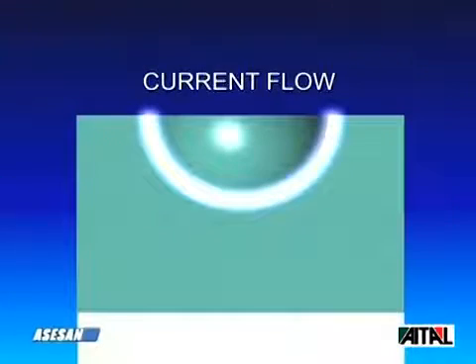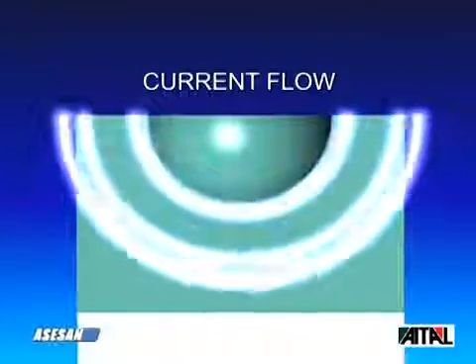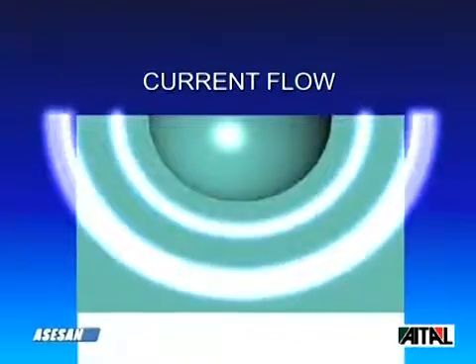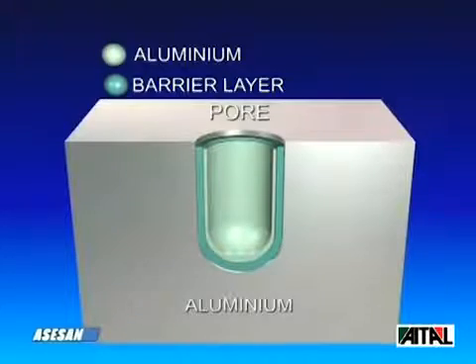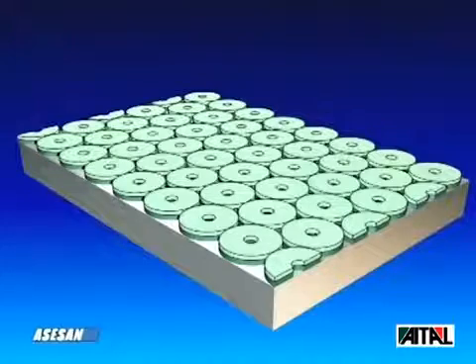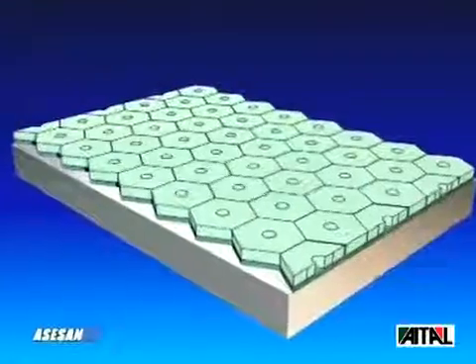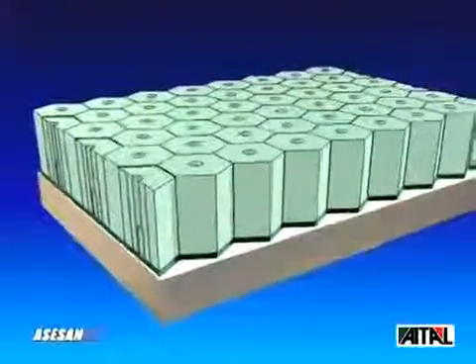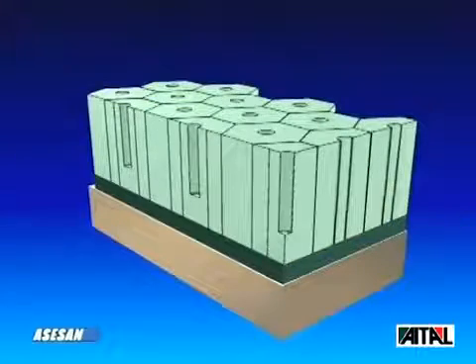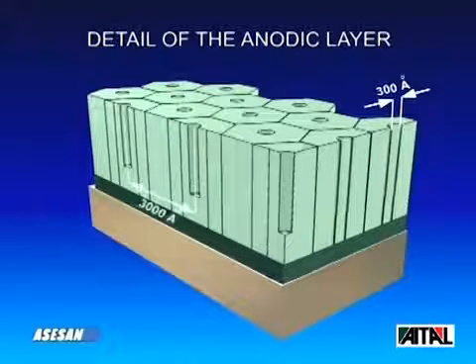At these attachment points, because they formed on the barrier layer before the oxide layer reached its maximum thickness, the passage of electrical current was facilitated. The current is distributed in a radial manner with respect to the pore, which will have a semi-spherical shape, so that the various columns of oxide in formation assume at first a cylindrical form, in whose axis we will find the pore. Finally, due to the equidistance between the pores, these cylinders will transform into hexagonal prisms. At the end of the process, a layer of aluminium oxide is formed that is perfectly adherent and chemically bonded to the metal base. There is no kind of coating on aluminium or any other metal that has the same adherence as the anodic film that forms in the process of anodic oxidation.